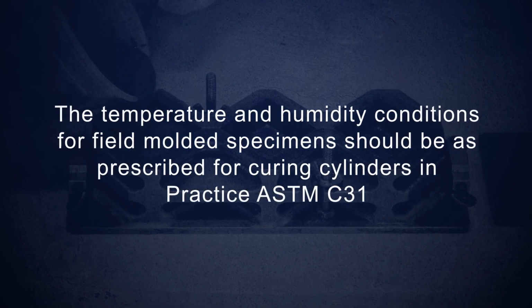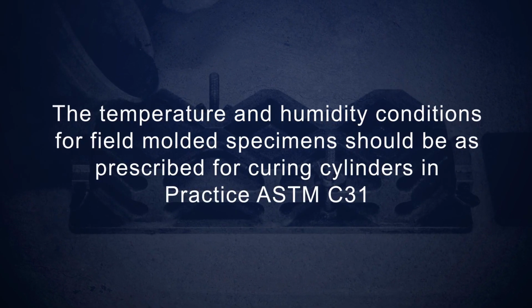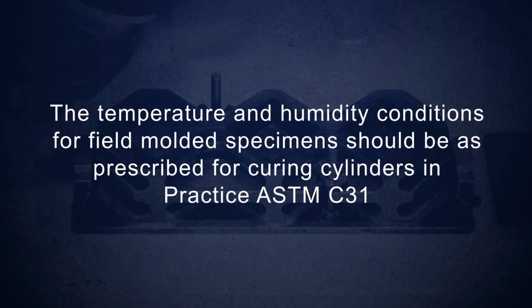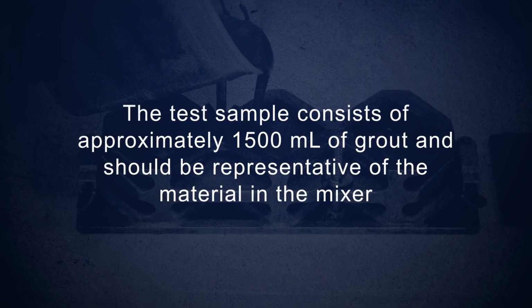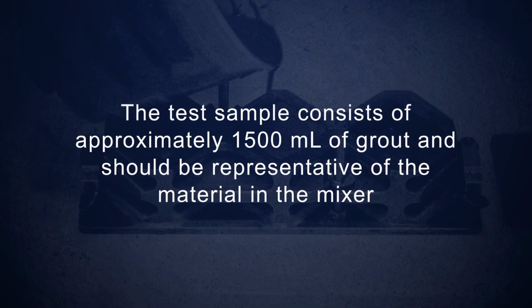The temperature and humidity conditions for field molded specimens should be prescribed for curing cylinders in practice ASTM C31. The test sample consists of approximately 1,500 milliliters of grout and should be representative of the material in the mixer.